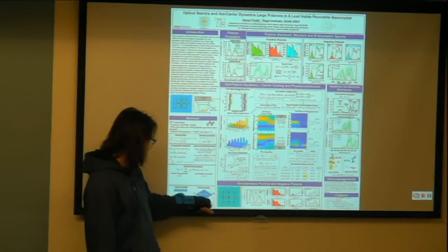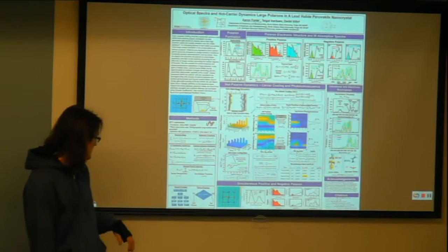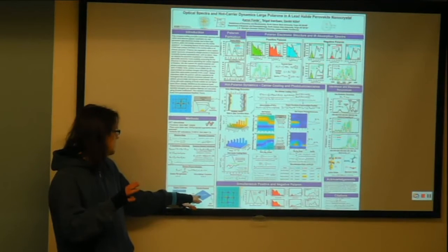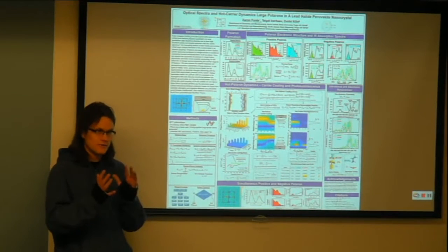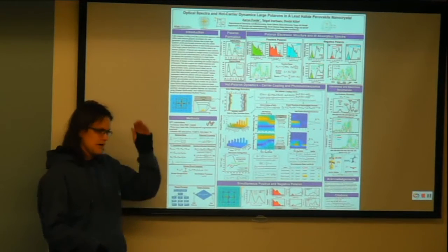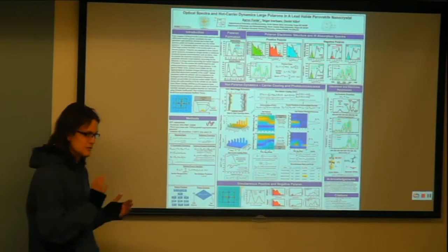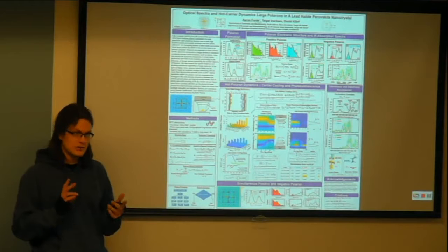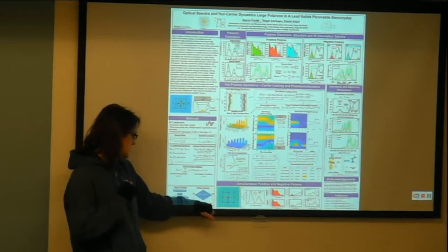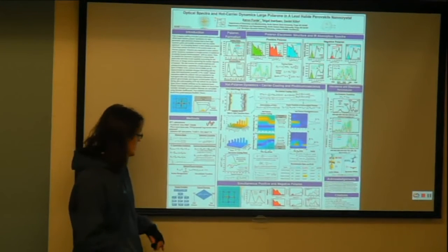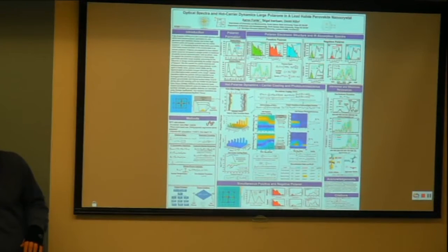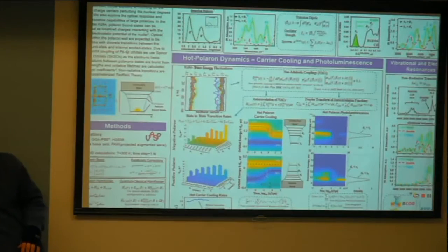And to interpret our excited state dynamics, there are 2 potential cases. Either you have a hot carrier and the lattice reorganizes quickly enough that it won't dissipate any of its energy, or the other case would be that it cools faster than the lattice reorganizes. So those would be 2 different physical situations. But the way that we set up our dynamics is to have a hot polaron and model its non-radiative relaxation. So that's how we attempt to model all of these observables.